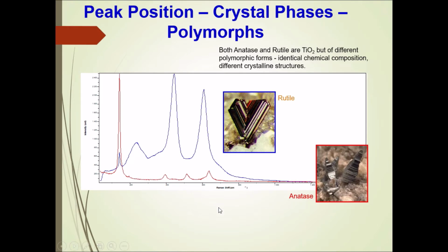Like in case of titanium dioxide, we have anatase and rutile structure. This red one is for anatase and this blue one for rutile structure. So using Raman, we can know if we have anatase or rutile, or we have a mixed phase from both rutile and anatase.